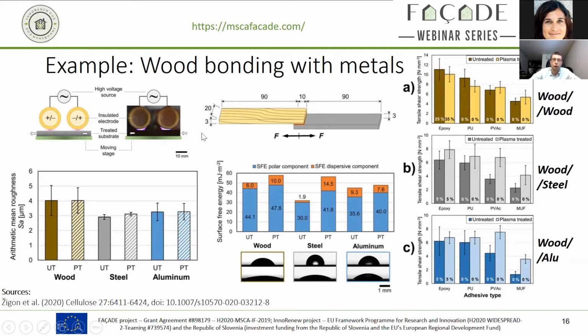We see for the plasma treatment that in some cases there's an impact on the roughness. For example, on steel substrates, the roughness was slightly increased. On aluminum and wood, there's no major difference in the micrometer roughness, as you can evaluate in the microscopes. However, in all cases, the surface free energy, both the polar and the non-polar components, were significantly modified.